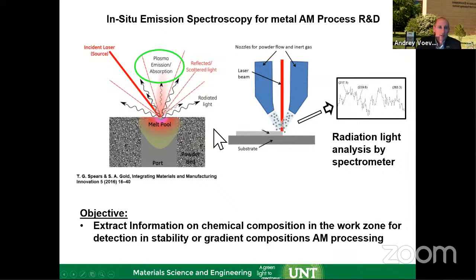If you have no variations, maybe it's not of interest, unless you start losing some low melting point materials such as aluminum and you want to compensate for that. But for gradient composition, in processes with direct feeding such as the LENS system, where you use nozzles to bring the powders from hoppers, you can vary the powder, so you can vary the elemental compositions in here. For that process, that's direct feedback.